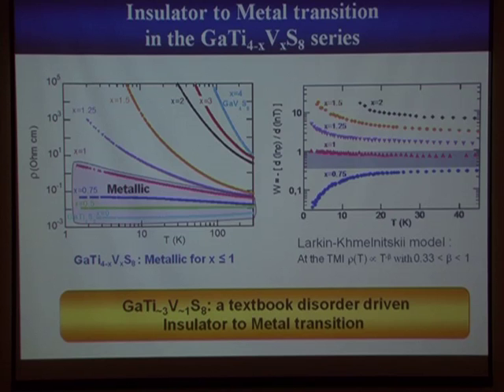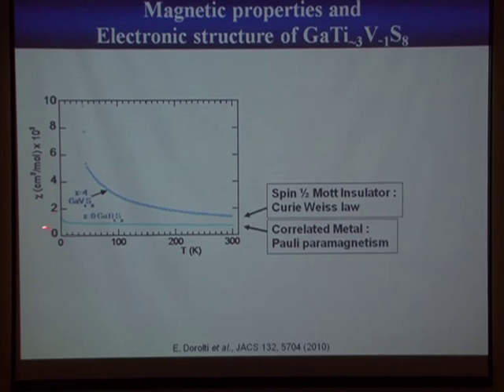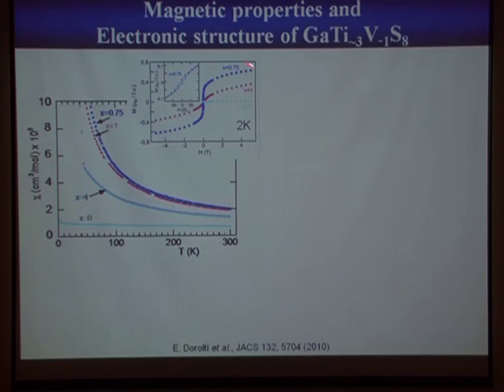Looking at magnetic properties: you start from a spin-1/2 Mott insulator with Curie-Weiss behavior and end with a metallic compound showing Pauli paramagnetism. However, on the metallic side of the transition the susceptibility still shows Curie-Weiss dependence, and at low temperature there is a ferromagnetic hysteresis loop. Band structure calculations show half-metallic behavior — zero density of states for one spin direction and non-zero for the other — explaining this ferromagnetic metallic character.